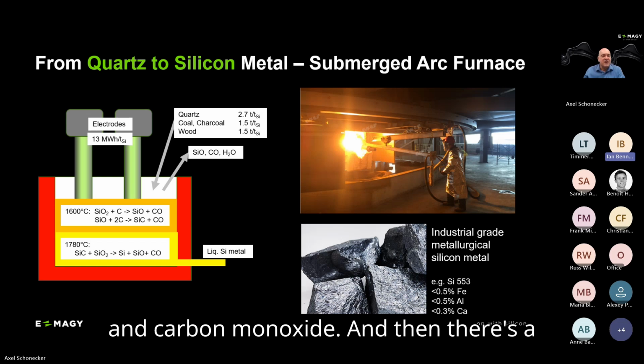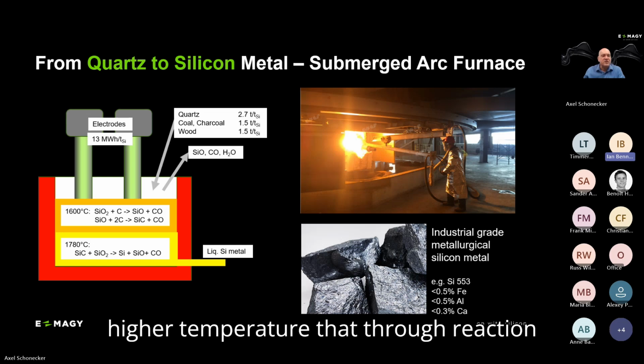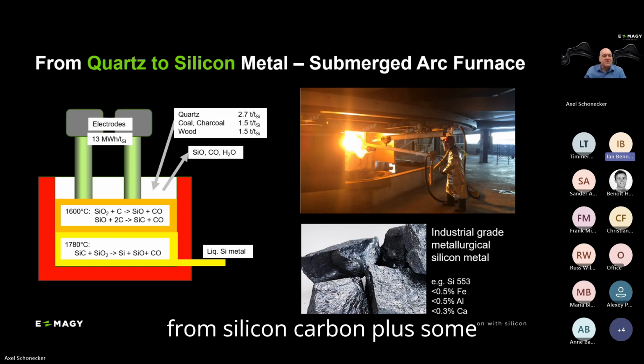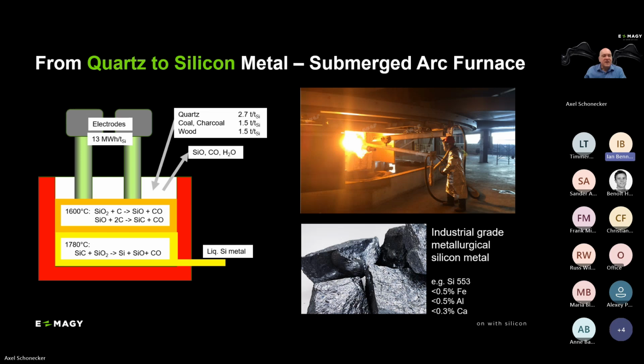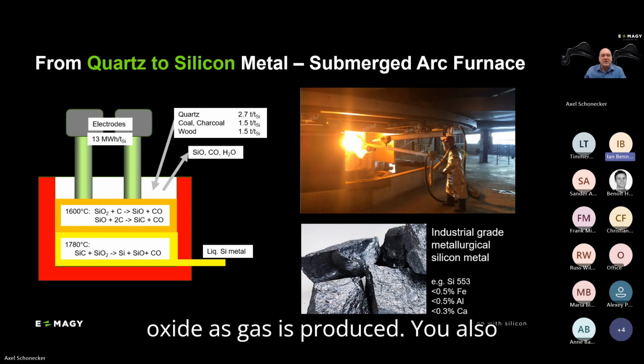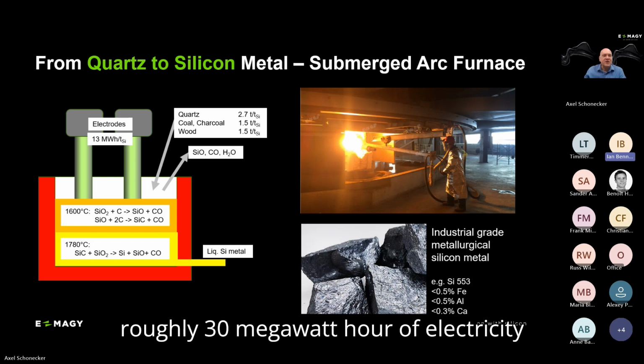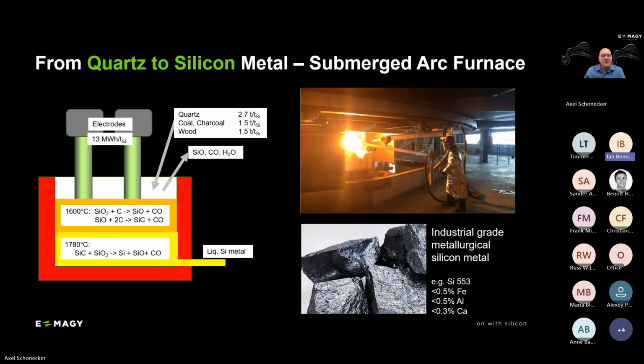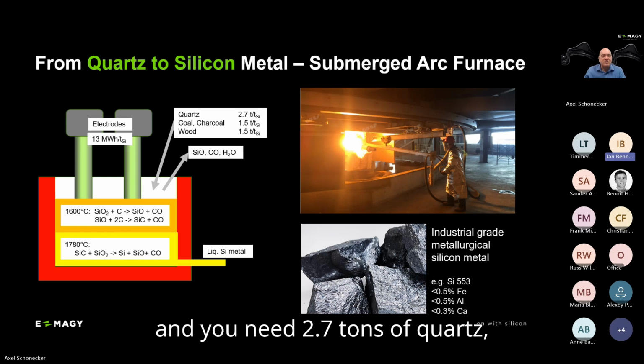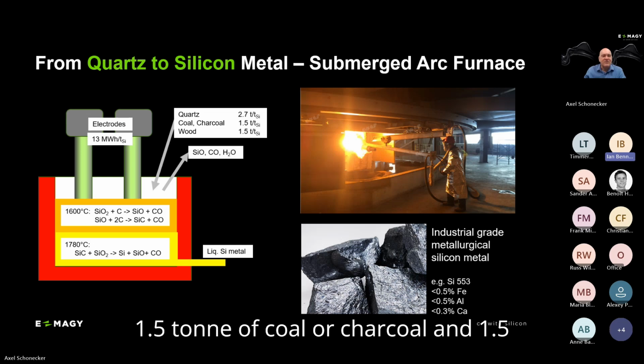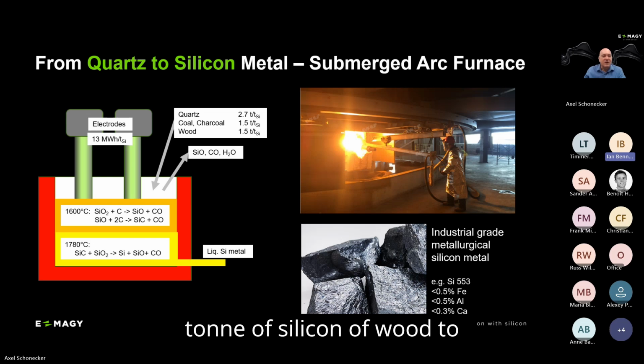And then at a higher temperature, through reaction of silicon carbon plus some quartz, you get the metallic silicon. And you have silicon oxide and carbon oxide as gas produced. You also see that per ton of silicon, you need roughly 30 megawatt hours of electricity, and you need 2.7 tons of quartz, 1.5 tons of coal or charcoal, and 1.5 tons of wood to produce that.